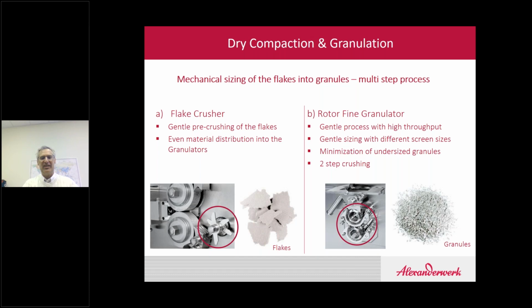The lower screen in the bottom RFG will control the top size of your material. And typically that might be about 1 or 1.2 or 1.5 millimeters, depending on the process that we're actually running. So by using this multi-step size reduction concept, we generate the minimal amount of fines possible.